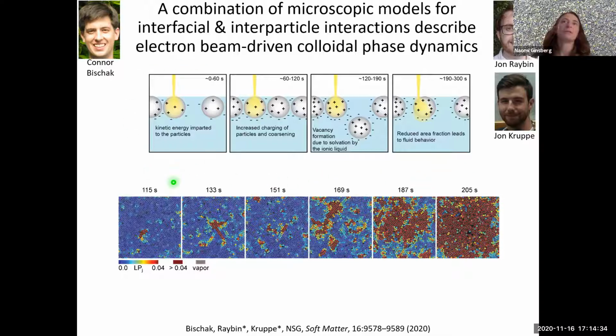Initially, the particles are close to charge neutral and are strongly pinned at the interface. They interact with one another through a Lennard-Jones potential. And then the electron beam charges the particles and the monolayer coarsens. And as the electron beam continues to charge the particles, they're screened more and more by the ionic liquid until they're unpinned. And this is basically causing a decrease in area fraction that's leading to this melting phase dynamics that we observe more macroscopically.